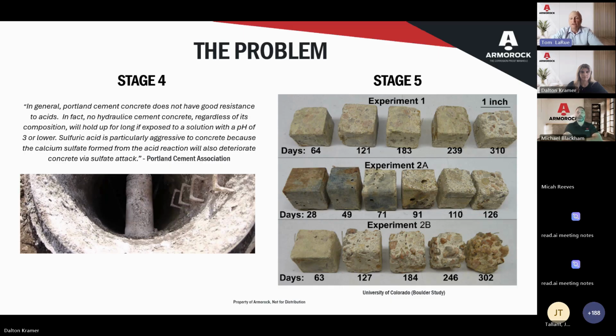Also, per Henry's law, and the way the sulfide behaves in the effluent, the sulfide exists in the effluent as H2S, as HS negative, and as S2 negative. As the pH decreases, the proportion of that leans more heavily toward H2S. So the pH is decreasing, the concentration of H2S is increasing, more gypsum is being created, exposing more concrete. It snowballs going downhill, rapidly increasing the rate of corrosion, which we see in the costs of repairing and maintaining